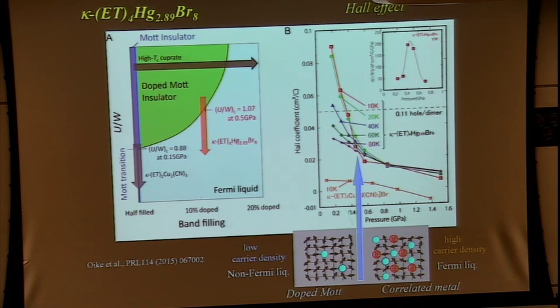So this is the cartoon. At low pressures, the mobile charges are very few, the carrier density is low, but at high pressures, there are many carriers. So we speculate this is a sort of Mott transition. Double occupancy is prohibited and allowed, crudely speaking. So in these high pressure regions, all of the electrons participate in the conduction and contribute to the Fermi surface, a large Fermi surface here. But at low pressures, only a small portion of the electrons contribute to the carriers. Probably the doped holes. So it's a holon, and other sites are occupied, accommodated by the spinons here. So in these regions, the spin, maybe the spinon, behaves like a spin liquid, as in the spin liquid insulators. And this doped hole is mobile. It contributes to the conductivity, high conductivity.